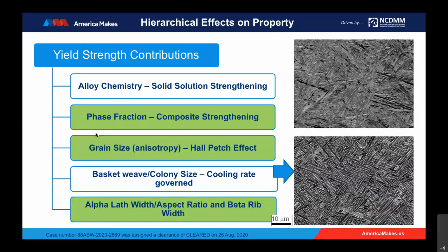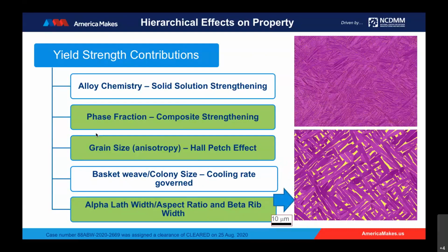And the last but not least is where we could get in the alpha lath width and the aspect ratio part of it, to be able to threshold these numbers and then use it through the deep learning tool that we have generated. That was really an important piece of information in terms of quantitative values that was added into the Bayesian hybrid model. So in the next charts, Shrikar will walk through the mechanical property response of the thin wall feature, which is feature 1.